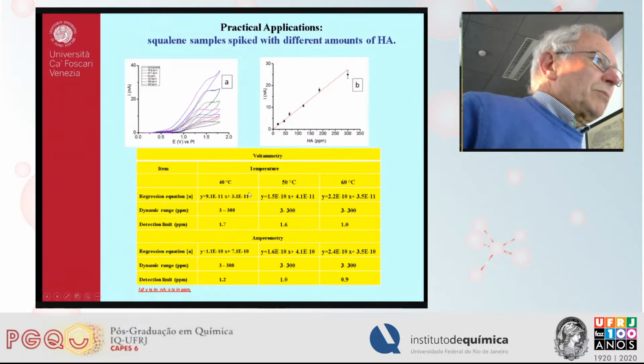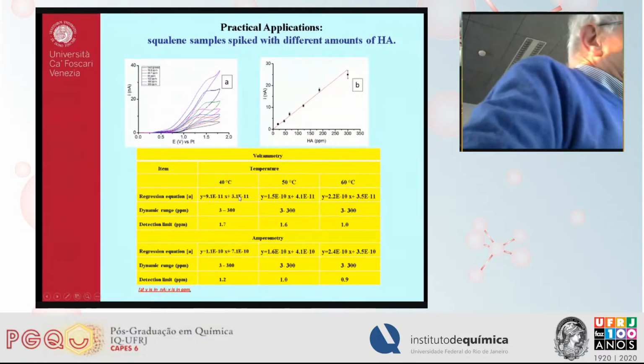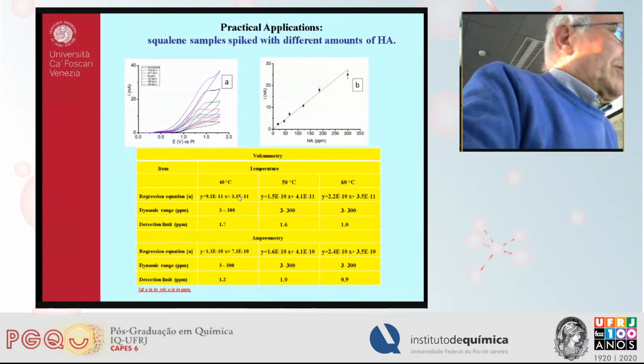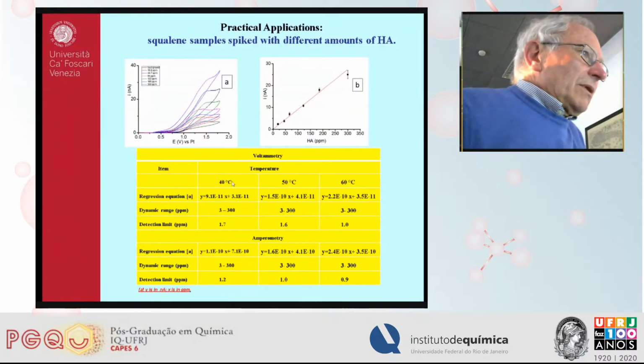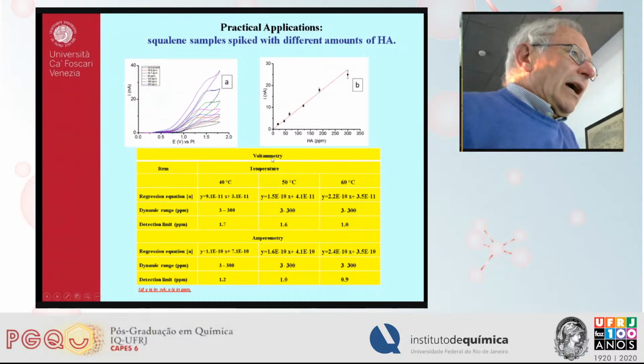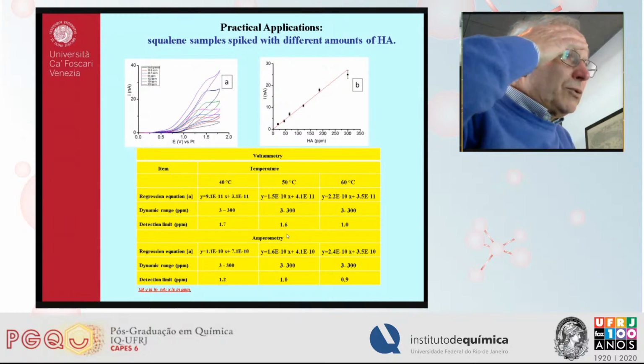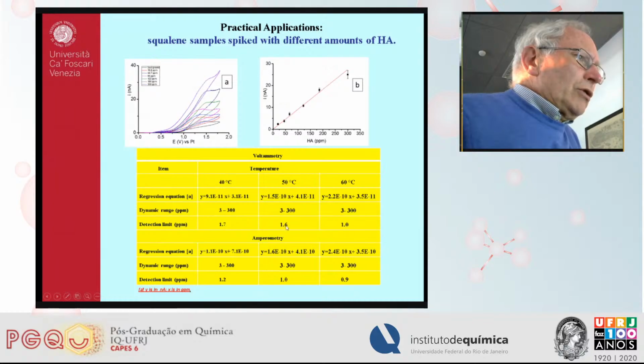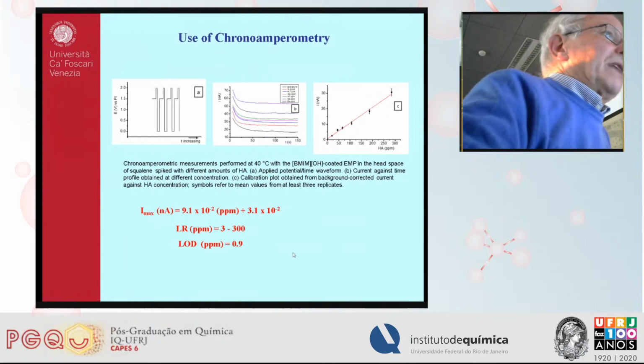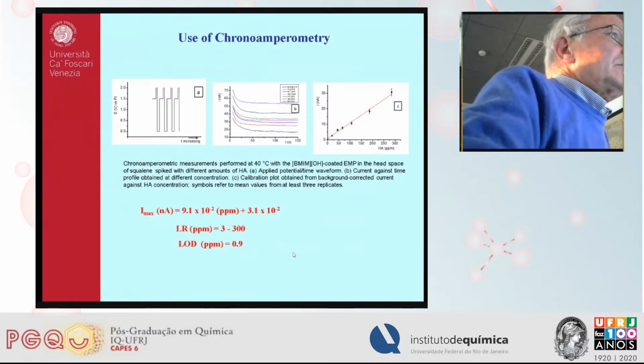So we made this measurement at different temperatures in order to verify the proportionality not only with the concentration but also with the temperature. These measurements were made by using either voltammetry, so we obtain waves like that, or amperometry, which provides current against time responses. Results were quite good with the two techniques. These are the detection limits obtained at the different temperatures, by voltammetry and amperometry. These are other examples in which we use chronoamperometry.